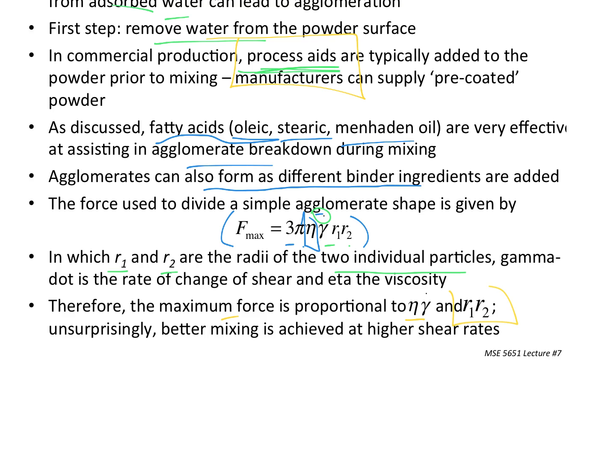Okay? And the issue here is that R1 and R2 may both be relatively large to begin with. So you've got this 100 micron hard agglomerate, pretty big in the scheme of things. You actually see 100 micron agglomerates with your naked eye. All right, but then as we become successful, R1 and R2 start to drop off dramatically. All right, and that's where it becomes very hard to maintain a high maximum force between two particles when those particles become very small. So this is kind of the milling limit for the system, because you can only exert so much force with a given shear rate and a given viscosity when R1 and R2 become very small. So eventually the process efficiency drops off to zero when you are successful, but hopefully that gives you a batch that you can injection mold. Any questions about that?